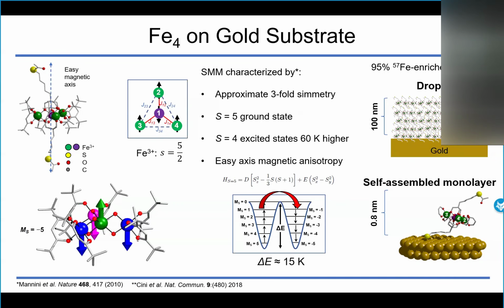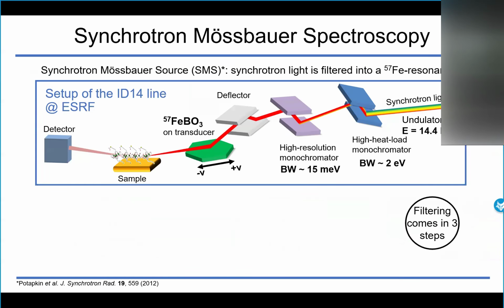As I said, the problem is that the standard setup does not have enough sensitivity to study these kinds of samples. This is why we consider the synchrotron light, and in particular the synchrotron Mössbauer source present at the ID14 beamline at the ESRF synchrotron in Grenoble. This is a sketch of the beamline. So how it works. The broad synchrotron light is then filtered such that only gamma rays with 14.4 kiloelectron volt are selected. Then the bandwidth is decreased in 3 steps.